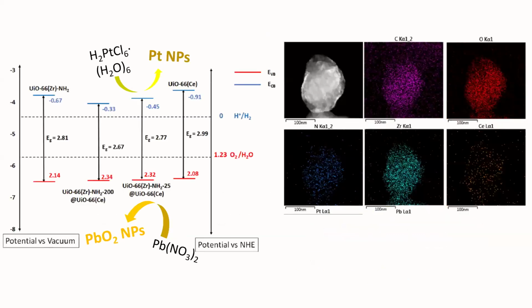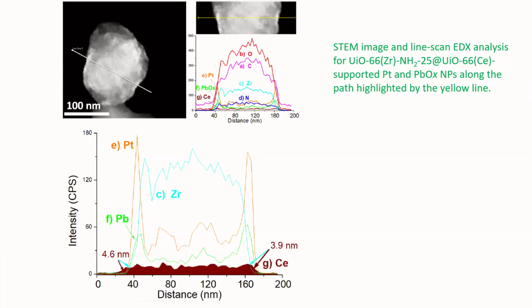After the synthesis, we deposited platinum nanoparticles and lead oxide nanoparticles to make sure which MOF is in the core and which MOF is in the shell. These nanoparticles were deposited, and these are the corresponding elemental maps, which show that inside we have zirconium and outside we have cerium. And this is the sample for UiO-66 zirconium amino 25 at UiO-66 cerium.